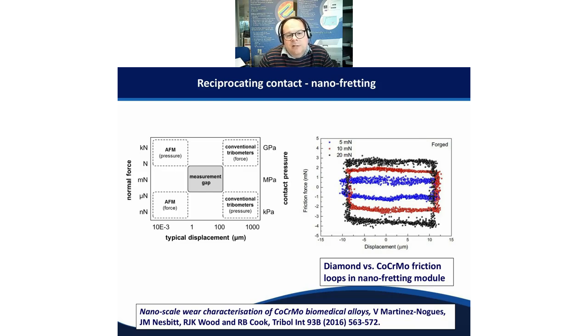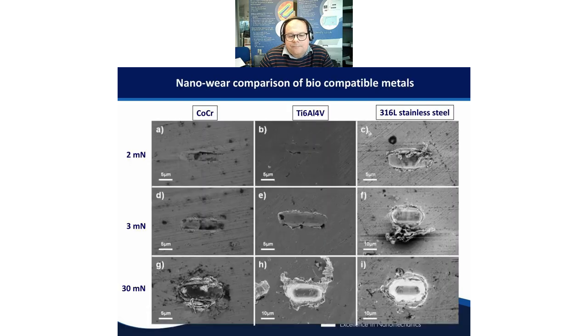And so this technique called nanofretting fills this gap between AFM-based tribo testing, which is obviously a valuable technique, but does reach limitations when you get to coatings which are much more than a few tens or hundreds of nanometers thick, and conventional tribometers which work at a scale which is too large. So the fretting technique drops nicely in that gap where previously there wasn't an instrumented suitable technique.